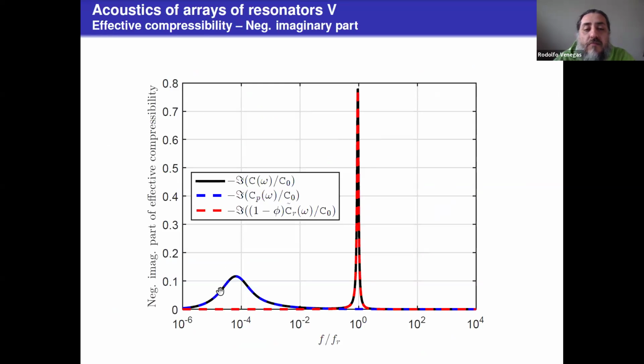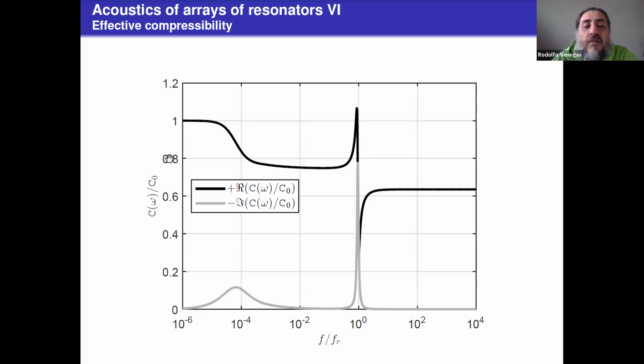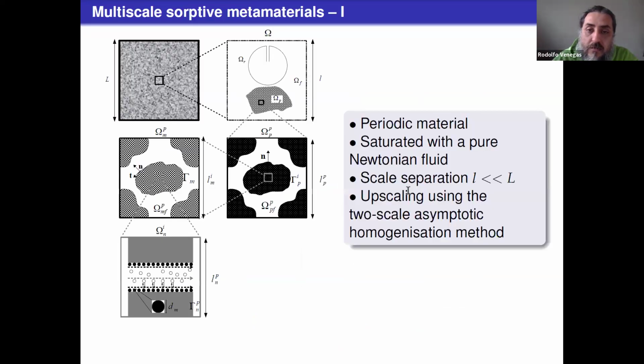In terms of the imaginary part, here we have the classical picture, and in this case related to heat transfer in the pore. And at the resonant frequency, we have a sharp increase of the imaginary part that will lead to sound energy dissipation. So that's just the compressibility of this array. So we have some interesting behavior around the resonance frequency of the resonators. And now the idea is to combine these two types of media.